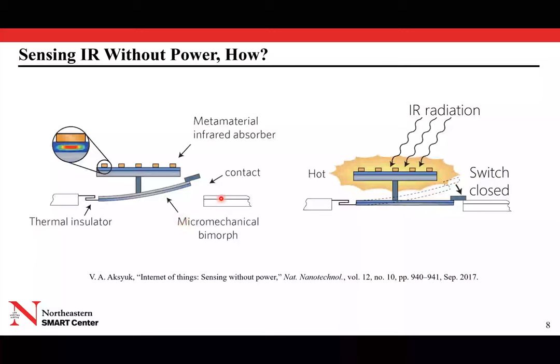So here is a very simplified cartoon that describes how this device actually works. The basic idea is that we use a micromechanical bimorph cantilever. It's a cantilever made out of two materials with two different thermal coefficients of expansion. So basically, when the cantilever heats up, it bends down, right? Now one end of this cantilever is connected to the substrate through a thermally insulating link, while the other end of the cantilever carries a contact tip.